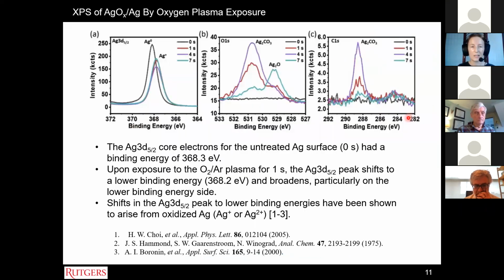So we conducted some XPS measurements of the silver after exposure to oxygen plasma for different times. And you can see clearly that there is a shift to lower binding energy as we increase the time. And this is sort of unusual for metals, but it's commonly seen for silver oxides that there's this shift to lower binding energy when you form different types of silver oxides, either Ag+ or Ag2+ based oxides. And in our case, we were seeing Ag+.